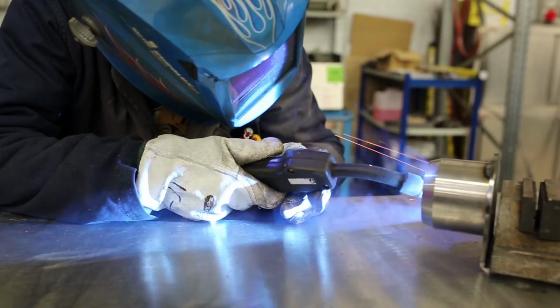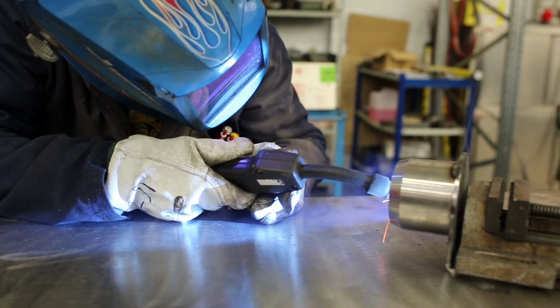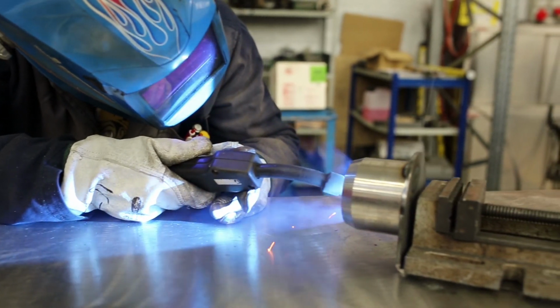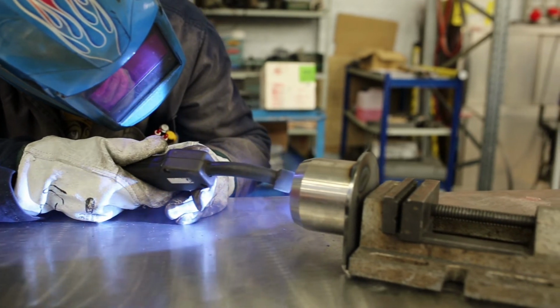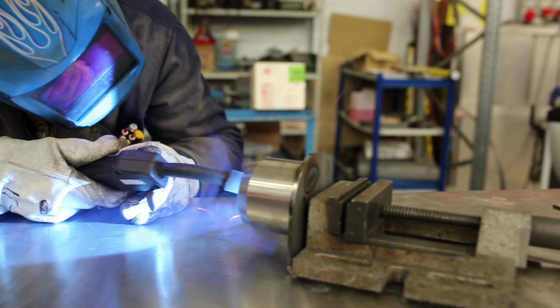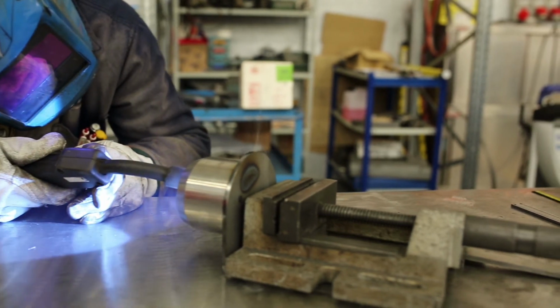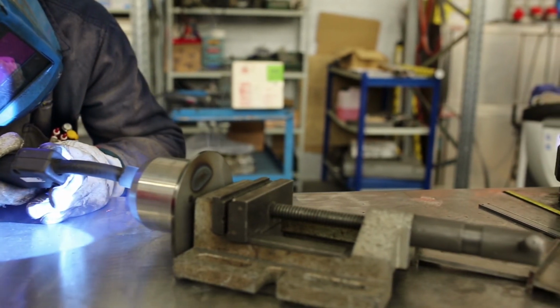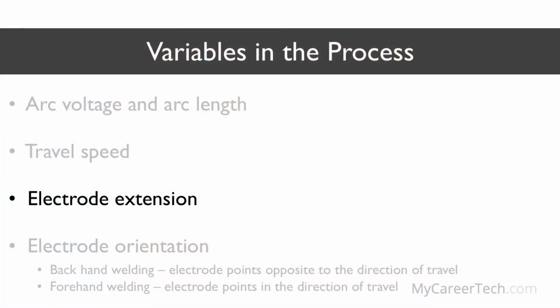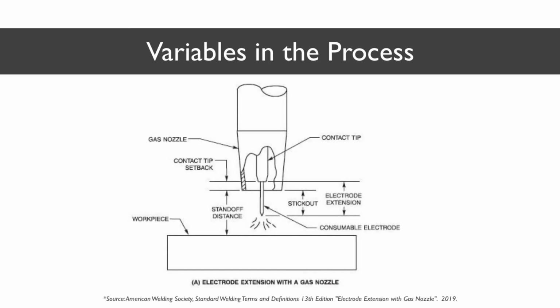When the travel speed's too slow, too much heat is introduced into the weld, resulting in an excessively wide weld bead and poor penetration. When the travel speed's too fast, it can cause a narrow convex bead, insufficient penetration, and an inconsistent weld bead. Undercutting may also occur with faster travel speeds, resulting in a weak weld. Electrode extension, or stick out, is defined as the distance from the contact tip to the end of the electrode, which is controlled by the welder and the machine settings. An increase in the electrode extension generally produces a narrow, high-crowned weld bead due to the increased resistance, which lowers weld current and the heat available to melt the wire.